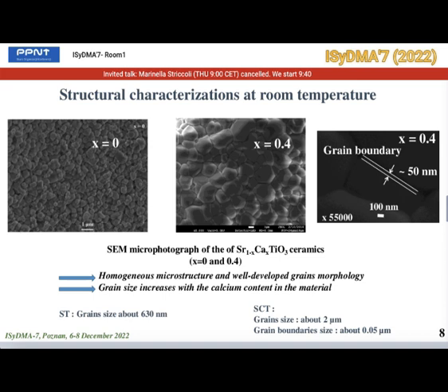Here we can see the SEM photographs of the ST and SCT ceramics. The microphotographs show a homogeneous microstructure and well-developed grain morphologies. We can see that the grain size increases with the substitution of calcium in SrTiO3 material. The average grain size is about 630 nanometers for ST and about 2 micrometers for SCT ceramics. The grain boundaries size is about, as we can see here, 50 nanometers.